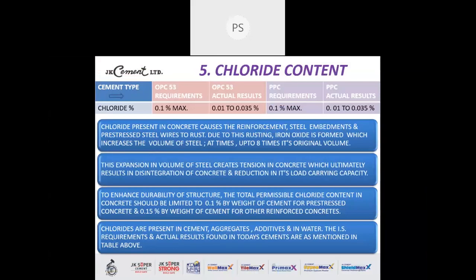Now, the fifth point is the chloride content. If you look at the chloride content, it should be maximum 0.1% only. For OPC 53, the actual result range in India is between 0.01 to 0.035%. The PPC requirement again is the same, 0.1% maximum. The PPC actual results are between 0.01 to 0.035%.